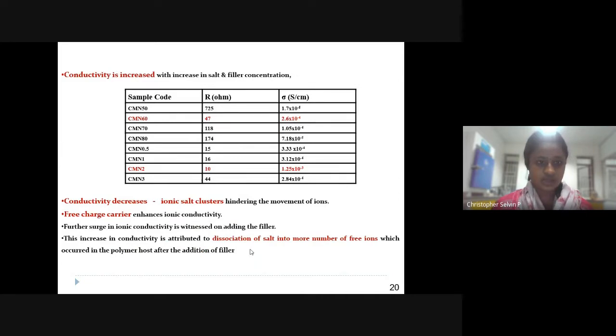These are the ionic conductivity values that have been calculated using the resistance obtained from the Nyquist plots. As you can see, the conductivity has been found to decrease at higher salt concentrations. This is because of the salt clusters that have been formed, hindering the movement of the ions. So this indicates that free charge carriers are needed to enhance ionic conductivity. That is the reason we have added filler to enhance the ionic conductivity, which has been observed. This increase in ionic conductivity is attributed to the dissociation of salt into a greater number of free ions, which occur in the polymer host after the addition of filler.